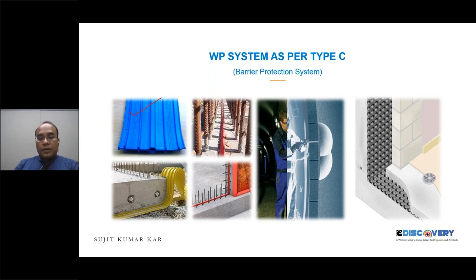The advanced system is this kind of swellable water bar, which is only placed by using adhesives or by making grooves, and when the second lift of the concrete is cast, it will be completely embedded in between the joints. And when water enters in future, wherever there is any weaker section of a joint, and the water comes into contact with these water stoppers, then it swells. It swells up to 30% to 40%, with a very controlled expansion during a 42 hours to 72 hours time.